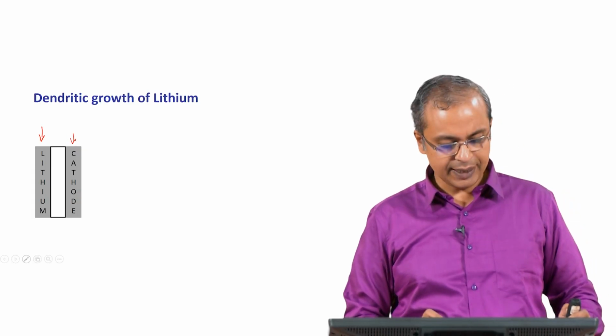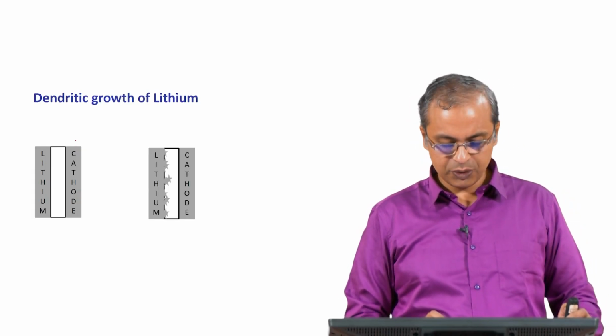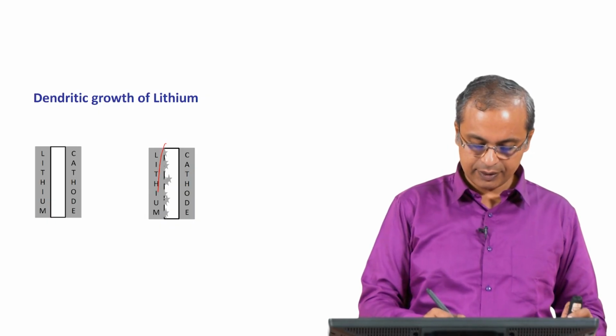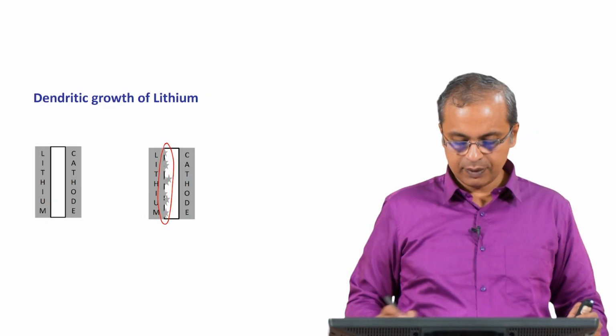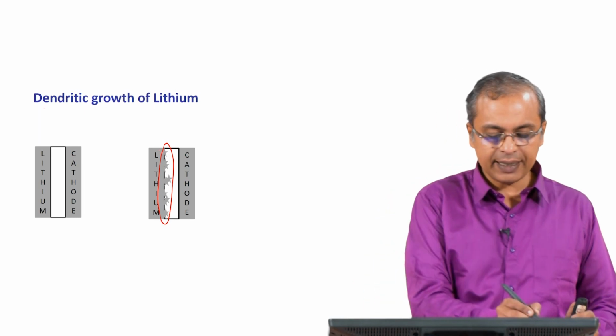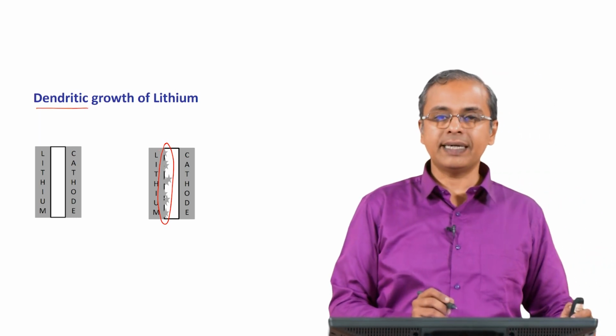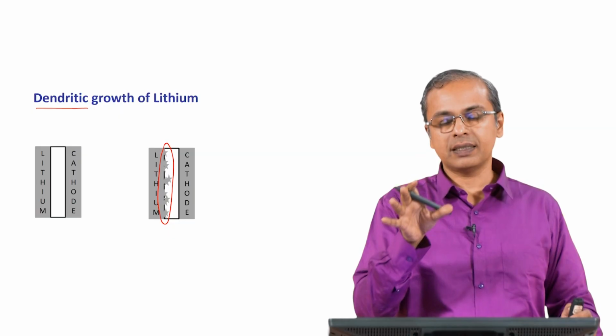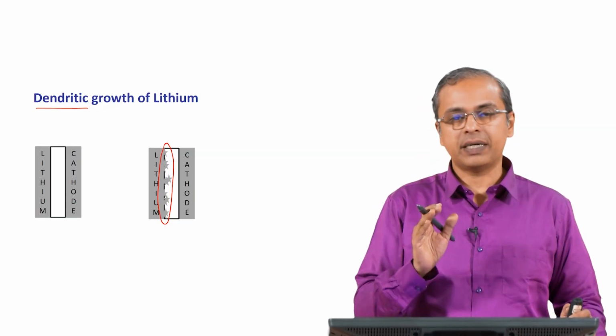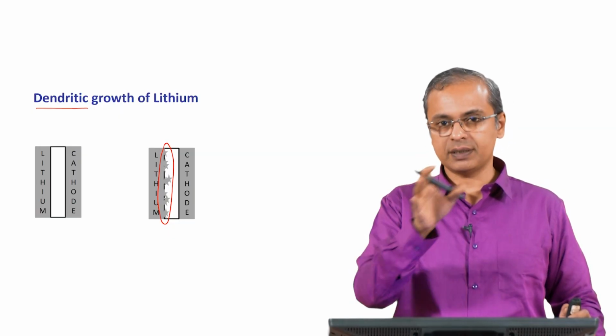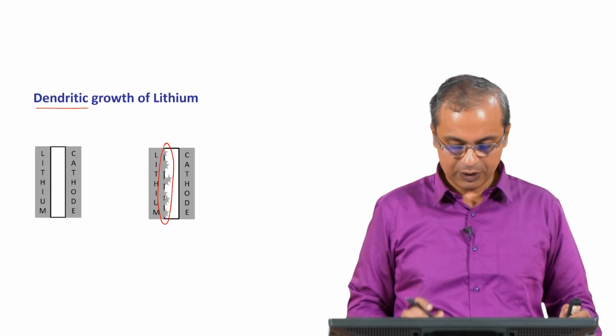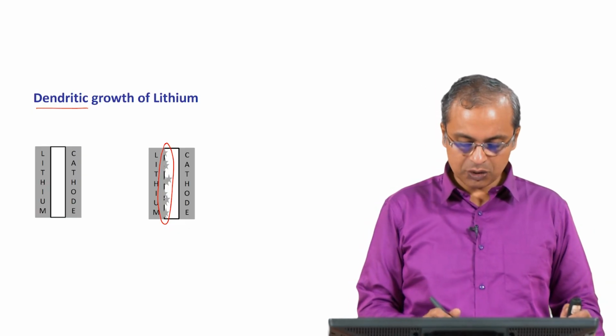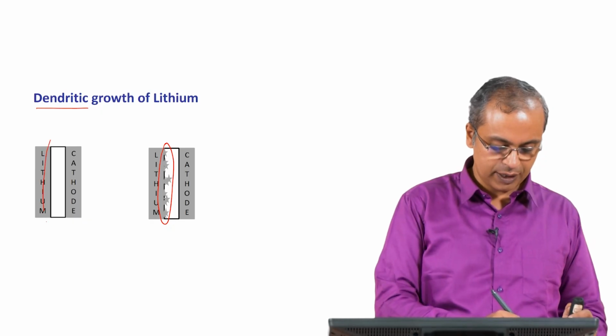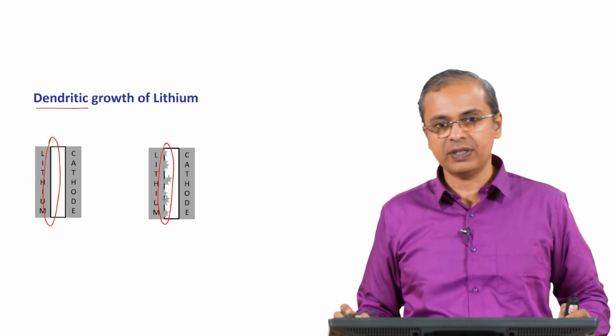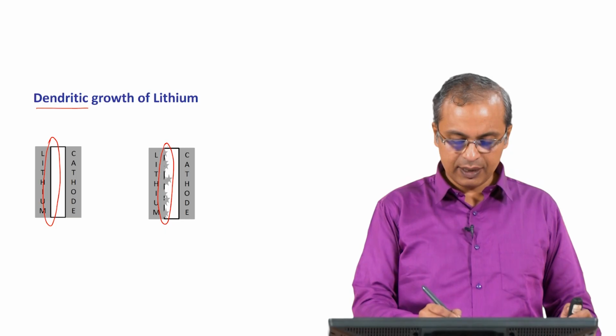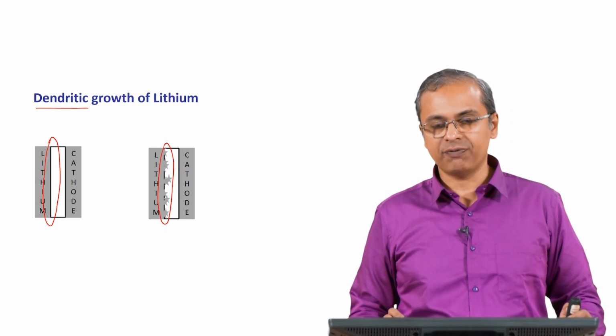So, let us say you cycle it, then what happens is you start seeing this uneven structure here, right. So, this is called dendritic growth. This kind of growth is called dendritic growth because it represents a structure that looks like dendrites, this kind of pointy structure which is growing in different directions. So, you can see that this is not plated back as uniformly as you see here.